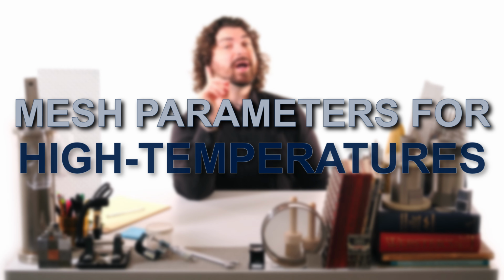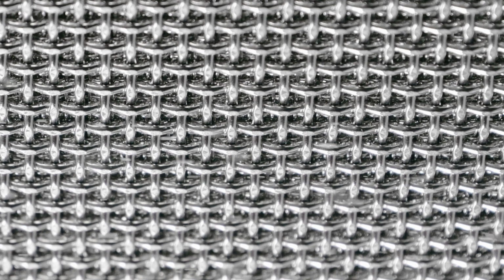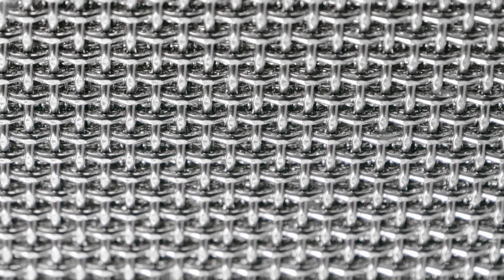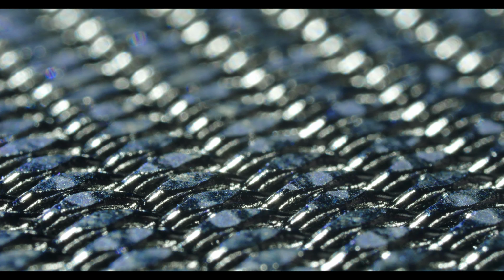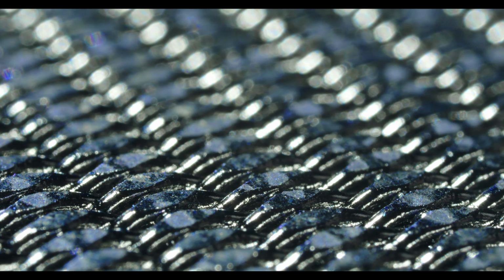Hot gas filtration is about more than just capturing particles. It's about doing so under punishing conditions, where temperatures can soar past 600 degrees Celsius and corrosive compounds attack every surface. At these extremes, the mesh must maintain structural integrity while delivering consistent filtration performance. This is why specifications such as pore distribution, permeability, total porosity, and laminate thickness are critical. These parameters dictate how the filter handles pressure drop, how quickly a filter cake forms, and how effectively the system recovers after back pulsing cleaning cycles. A poorly specified mesh can lead to unstable pressure drop, frequent cleaning cycles, and even catastrophic failure.